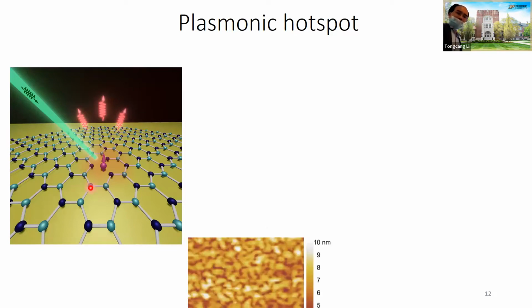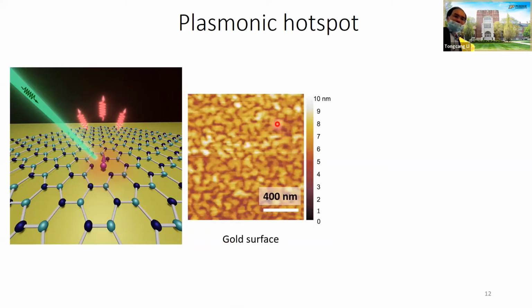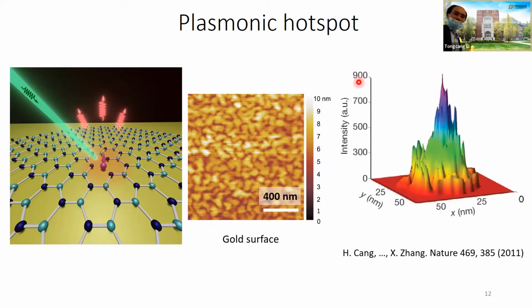If you look at the gold film with AFM, you can see it's smooth, but not perfectly smooth. The average roughness is only 1 or 2 nanometers, but peak to peak can be about 10 nanometers. And this is enough to support localized plasmons. There's work done before on hot spots. The hot spots from surface roughness naturally have a size on the order of 20 to 50 nanometers. So with these hot spots, you can form a tiny optical cavity with a size on the order of 50 nanometers. That can give you pretty good Purcell enhancement to increase the brightness.